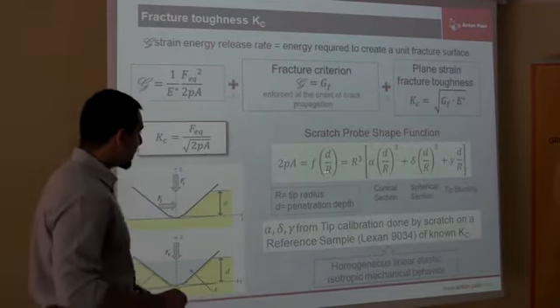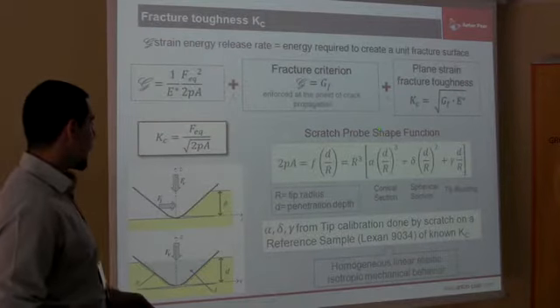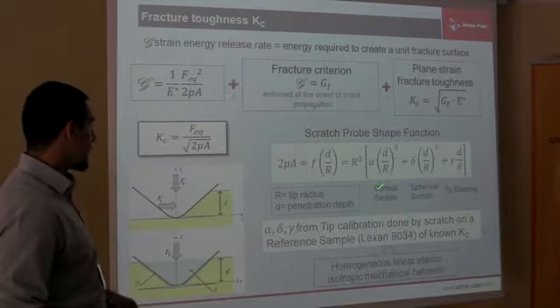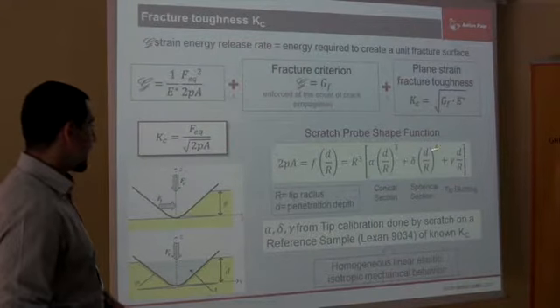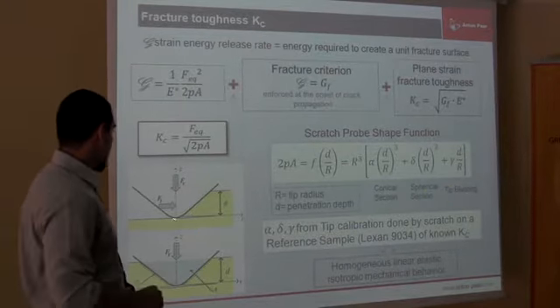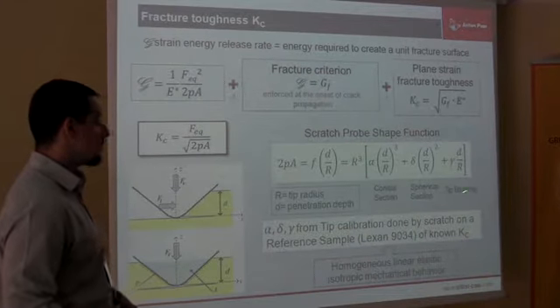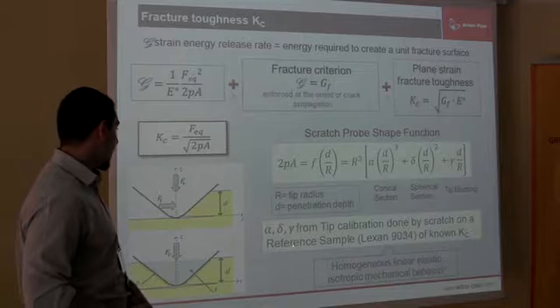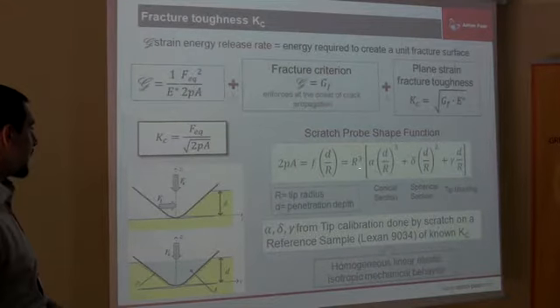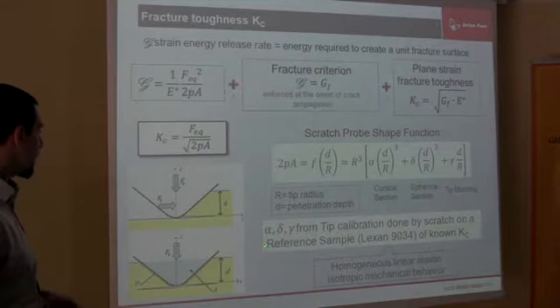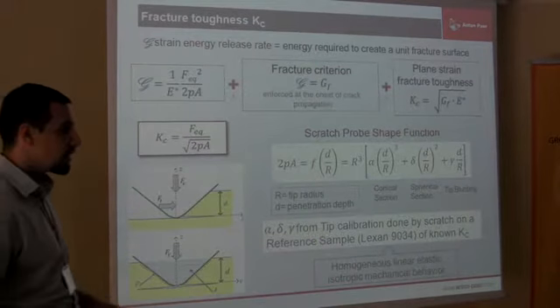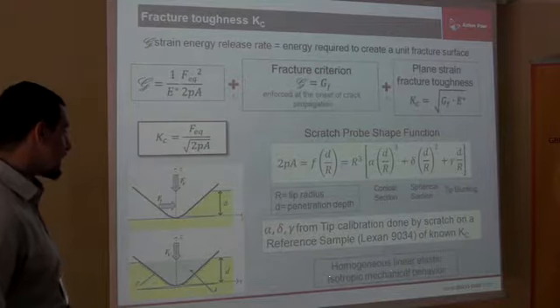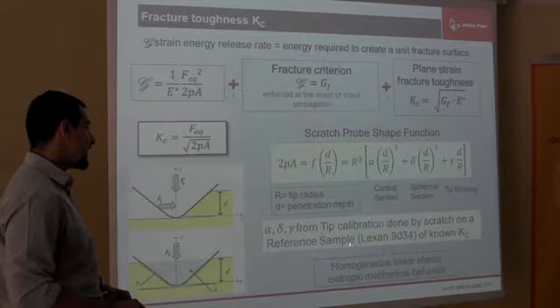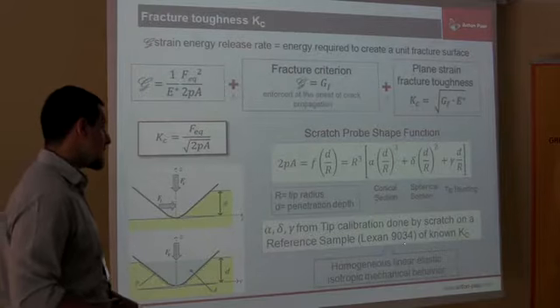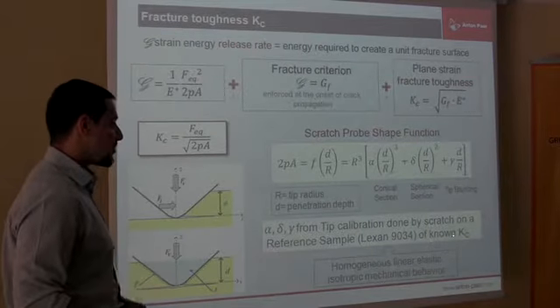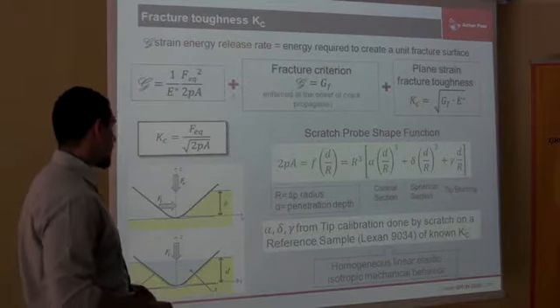This function is presented for a Rockwell tip, and here we have the conical part of the tip, a parameter for the spherical end of the tip, and a part due to the tip blunting. So now we have to find these three parameters from a tip calibration, and we choose a homogeneous, linear elastic, isotropic mechanical behavior material, that is the Lexan 9034, because we know very well the fracture toughness of this material.